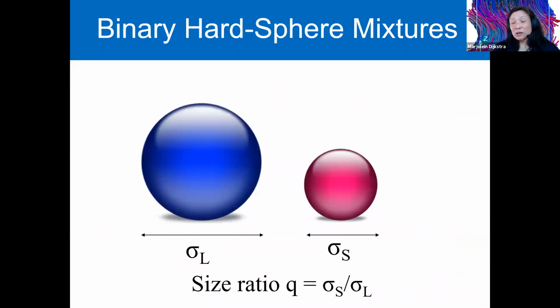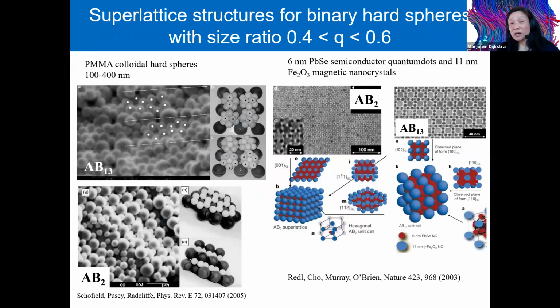So to increase the structures that one can make, one can also look at mixtures, big spheres and small spheres, determined by a size ratio q, which is the diameter ratio of the two spheres. If we consider, for instance, a size ratio of about a half, so the small spheres are twice as small as the big spheres, then one can get extremely exotic crystal phases.